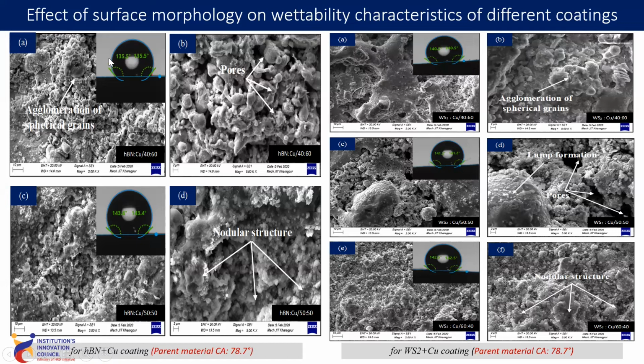This large contact angle was obtained by changing the mixing ratio. As you can see, this surface is 40:60 and this surface is 50:50 mixing ratio. When we increase the HBN, a large contact angle is obtained because HBN has an ability to repel the water. If it repels the water, this large contact angle is obtained.